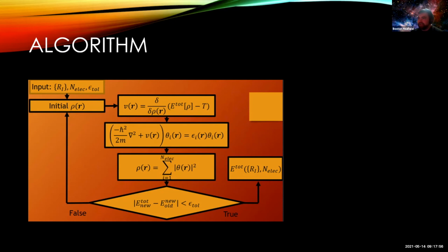Basically, you start with some initial conditions, and then it starts running through these equations and updating the total energies. It keeps looping through these until the total energy between individual steps is less than some energy cutoff value that you set. That should mean that you're at the minimum, the ground state energy, which is what you're generally trying to get to in these calculations. So you're self-consistent with itself. It just loops through and compares new values that it's calculated to the old values, and then keeps trying to get to the lowest potential that it can, and it calculates that through the density functionals. No, that's great. That's great. Yeah, thank you.